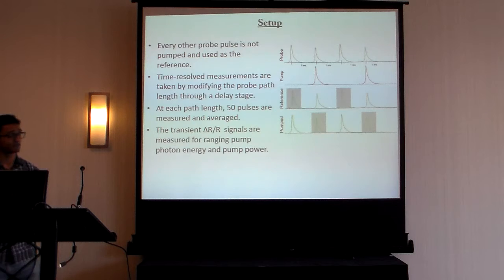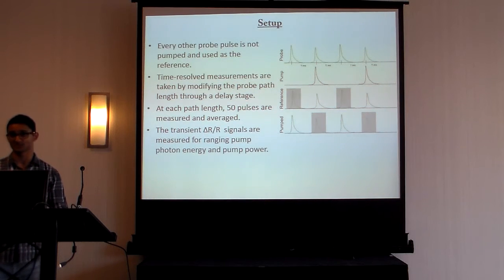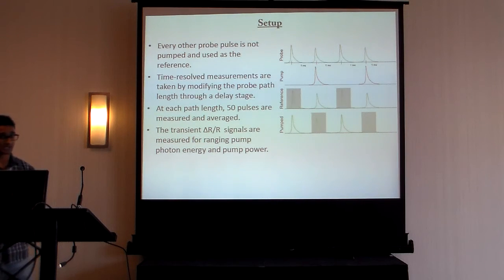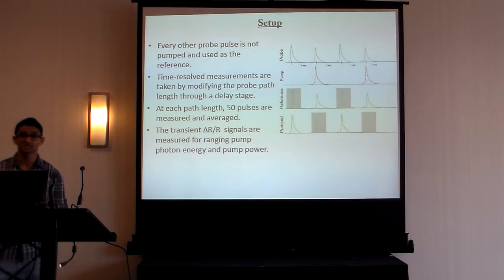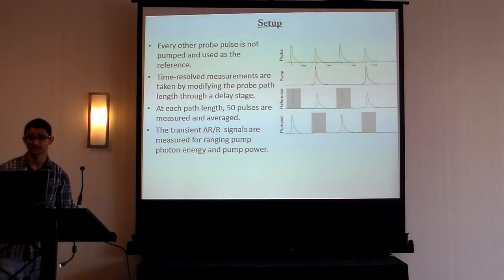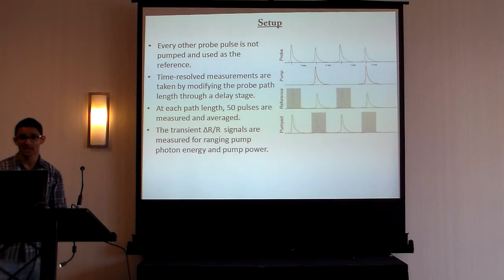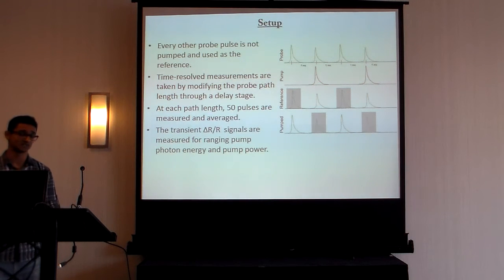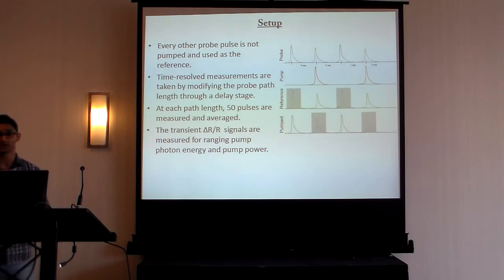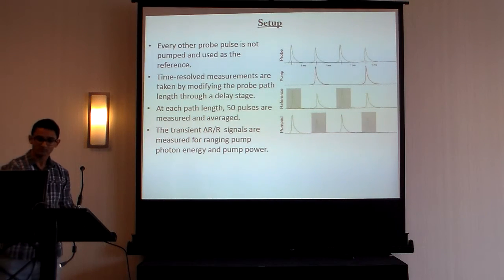So as I said earlier, every other pulse is not pumped and is used as a reference signal. We can take time-resolved measurements by modifying the path length of the probe beam with respect to the pump through an automated delay stage. At each path length, we measure over 50 pulses and average the data. And the transient reflectivity signal is taken for a wide range of pump photon energies and pump powers.